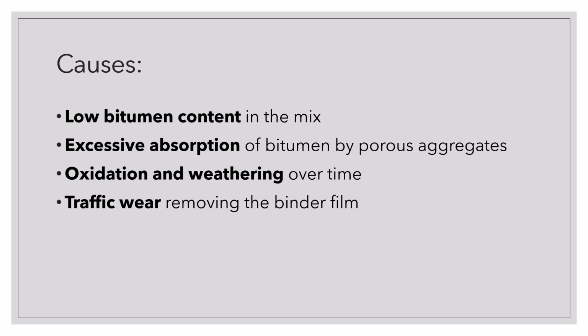One among them is low bitumen content in the mix. Next is excessive absorption of bitumen by the porous aggregates. If porous aggregates absorb the bitumen, then hungry surface can also occur. Next, oxidation and weathering. As time passes, oxidation and weathering also increase. Next is traffic wear, and this traffic wear removes the binder film that is coated on the aggregates.